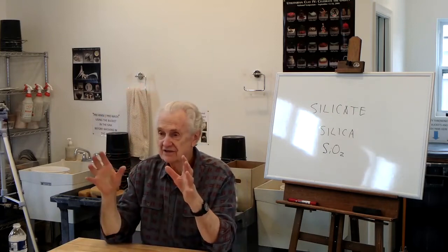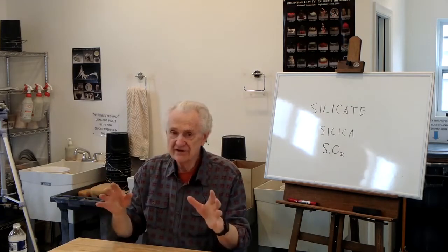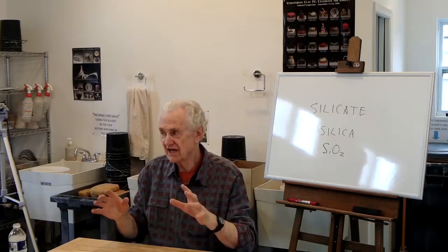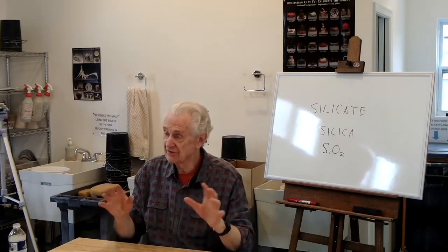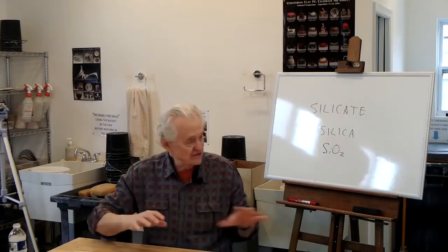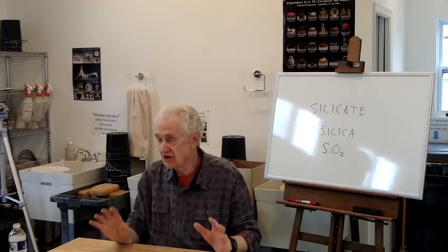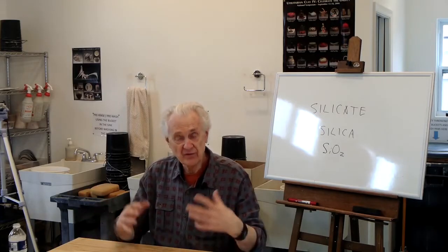And then as the kiln cools down, the glaze basically freezes. And the important point here is, in a lot of other materials, if we melted it and cooled it down, it would crystallize. It would form crystals. But because of these particular compositions, they don't. They freeze into this random arrangement, and they form a glass. And that's the glaze. So the glaze on pots is a coating of glass that we have applied to the pot.